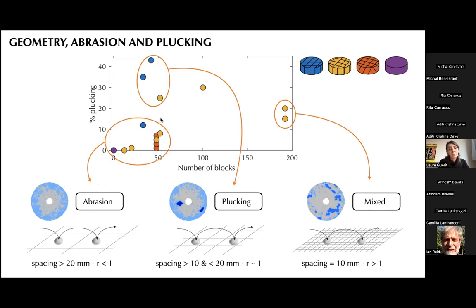At the top here, we find experiments dominated by plucking, with an intermediate number of fractures, and in this case, the size of the blocks scales with the size of the sediment. So we have a ratio of about 1, and this clearly favors plucking and thus high erosion rate. On the right here, we have the mixed experiment with a dense network, so that the size of the block is smaller than the size of the sediment. So there is some plucking, but it behaves as if it was in abrasion.